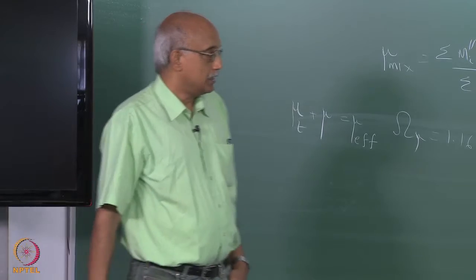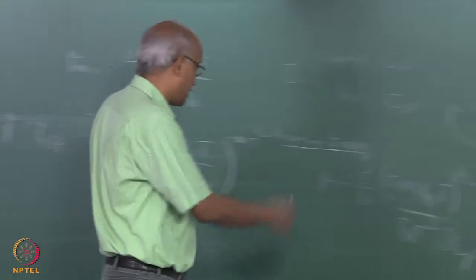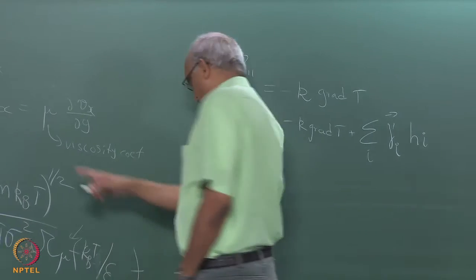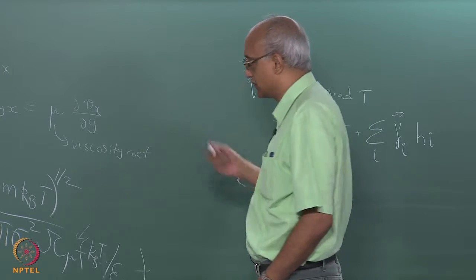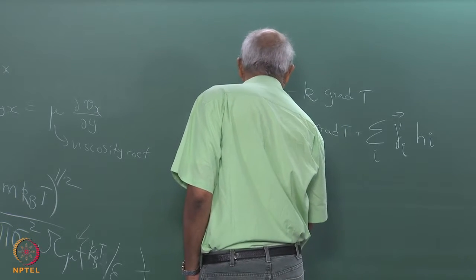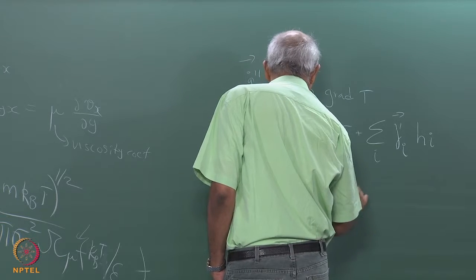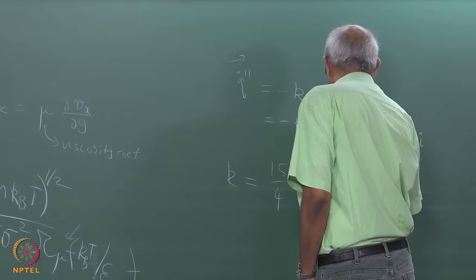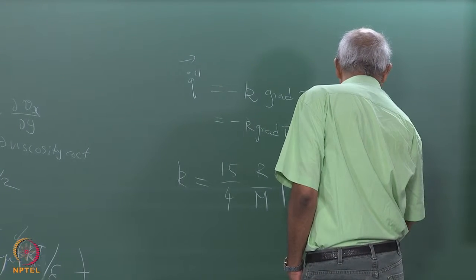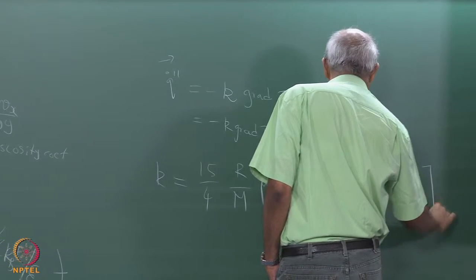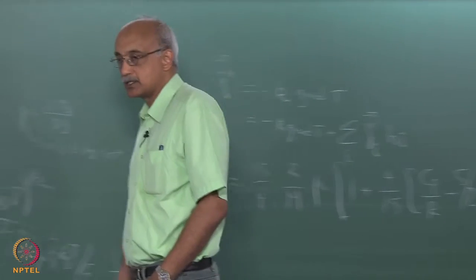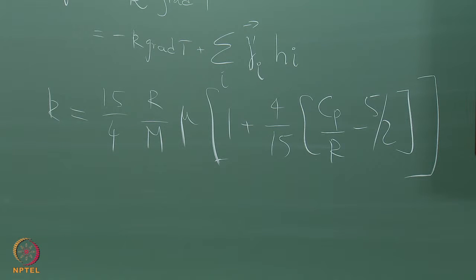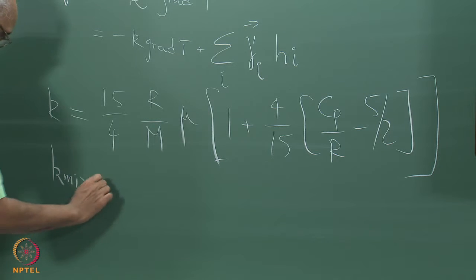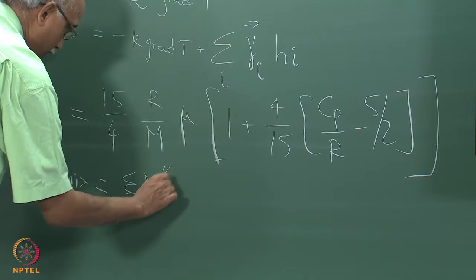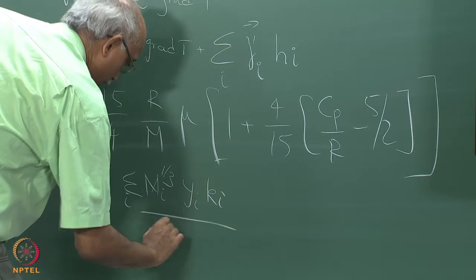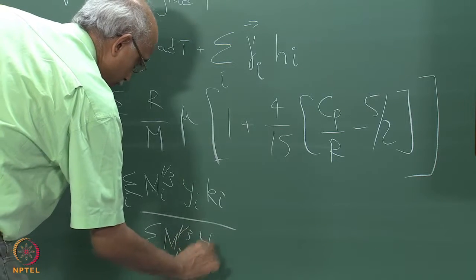So, here obviously the key parameter is your thermal conductivity K, and again the Chapman-Enskog theory says once you know what viscosity is, you can calculate K based on the viscosity of the fluid, and the formula for that is 15 by 4 times R by M times mu times 1 plus 4 by 15 times Cp by R minus 5 by 2, where Cp of course is the heat capacity at constant pressure, and K mix is summation over i of mi to the power 1/3 yi ki divided by summation over i of mi to the power 1/3 yi.